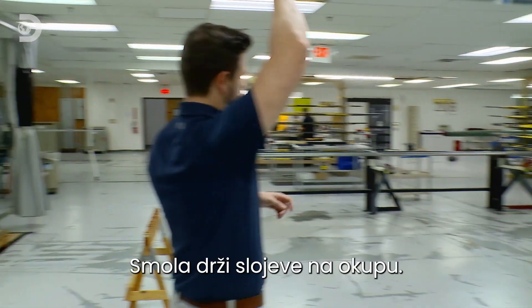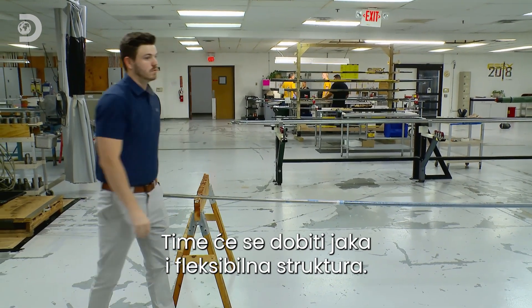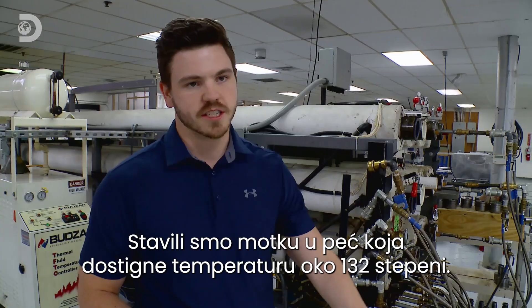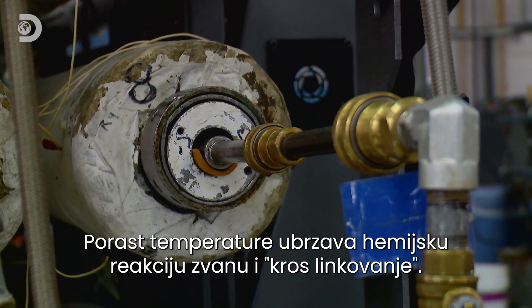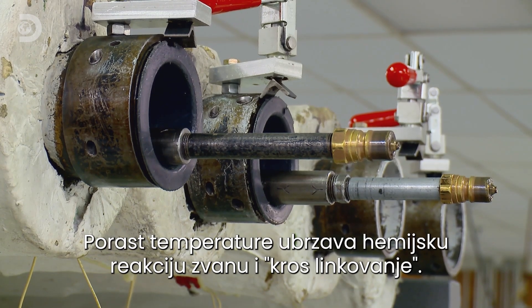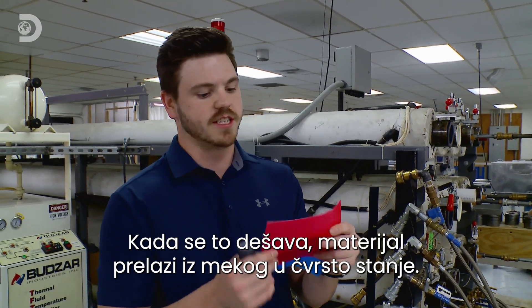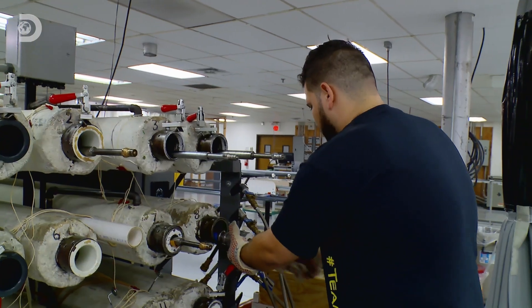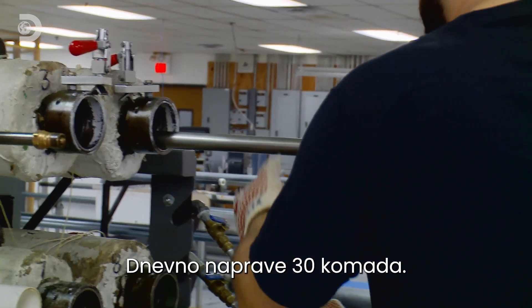To make it rigid, the material has to cure. The resin glues the layers together to create a strong and flexible structure — this happens in hot cylinders that work like an oven, heated up to about 270 degrees Celsius. This temperature rise accelerates the chemical reaction known as cross-linking, which takes the material from soft and malleable to hard and rigid. The poles bake for one hour and 20 minutes, and the factory makes up to 30 a day.